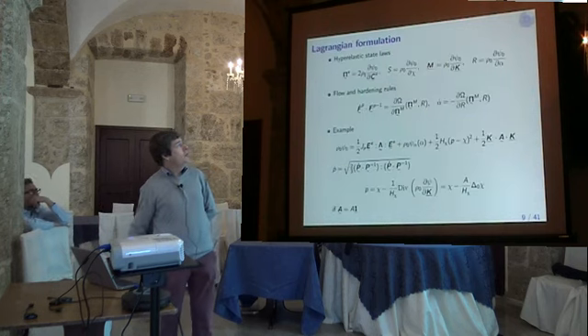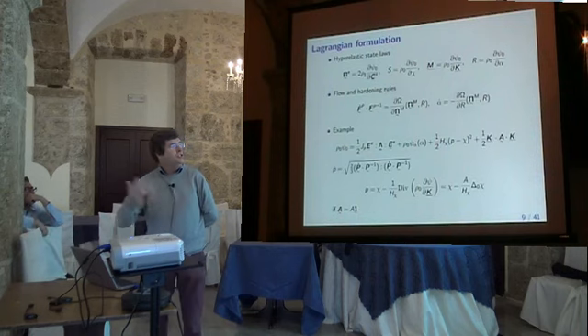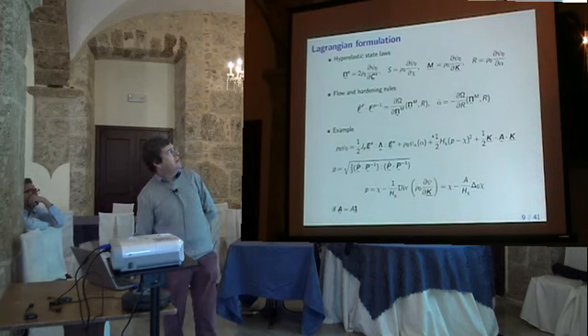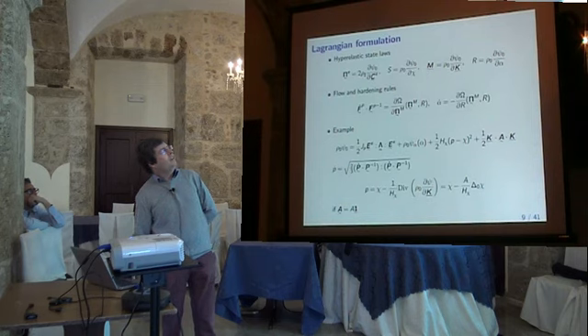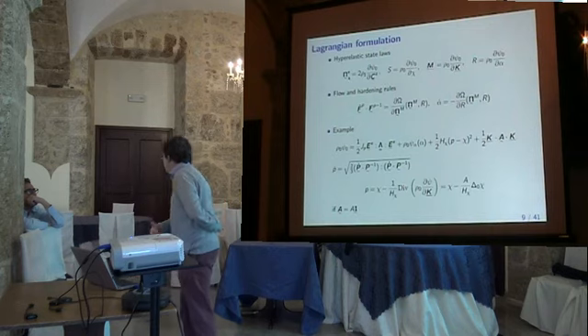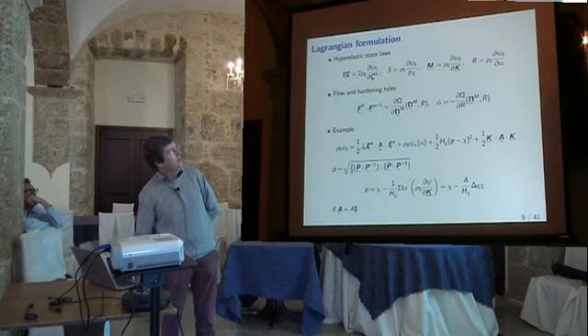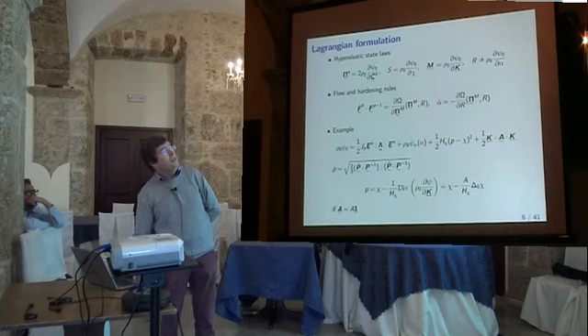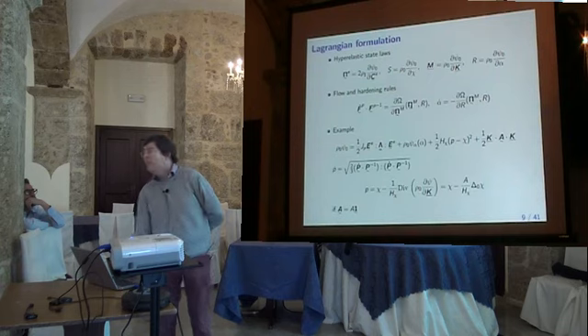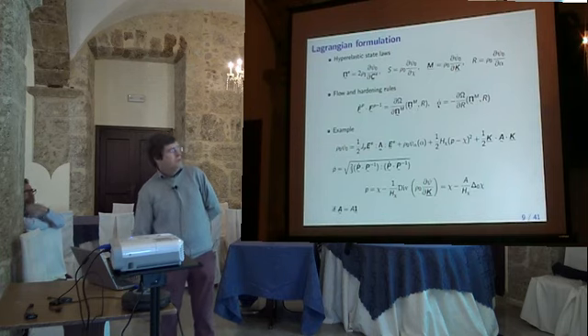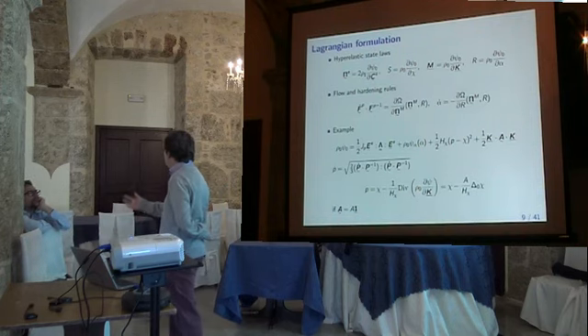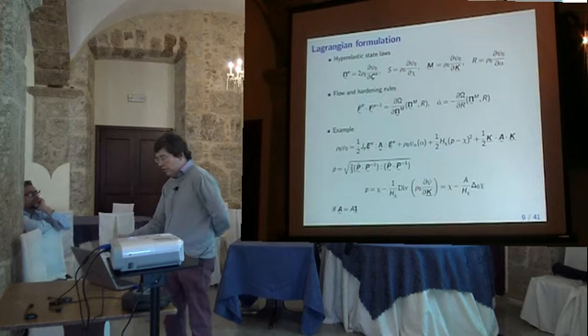And then you have the usual rules of thermodynamics. So you write your positivity of dissipation, and we propose a framework which is like this: hyperelasticity for all stress quantities. So I would say the elastic Piola stress here. So the relaxed stress on the intermediate configuration, the sort of generalized Piola for the micro deformation. And also coupled stresses, and this time they are Lagrangian, this one, because this is a Lagrange quantity. And the driving force for hardening or softening. And then the plastic flow is given by a dissipation potential, which is a function of the Mandel stress. And this is the idea. And the evolution equation, if we want it to be really a standard generalized material. So it is possible to still have the same framework in generalized continuum mechanics. The standard generalized framework is very similar.